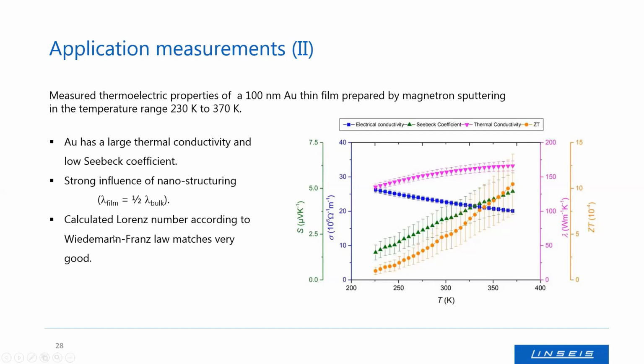We checked it by the so-called Wiedemann-Franz law, which holds for metals. It says dividing thermal conductivity by electric conductivity will give a constant value, the so-called Lorentz number. And the Lorentz number calculated from these results is in very good agreement with the literature value.